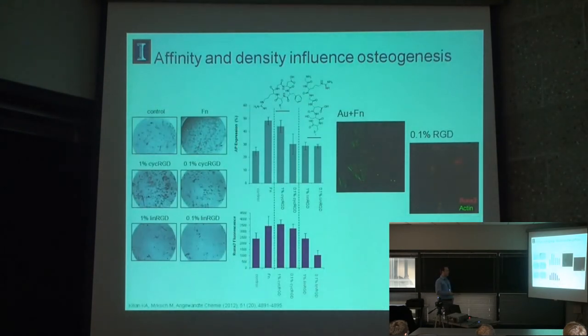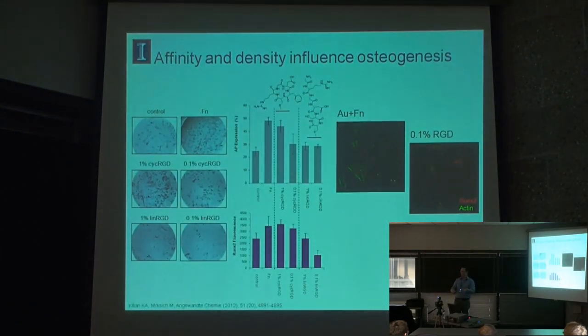And so in our first experiments, thankfully, we decided not to add a bunch of media. We just let them grow, and then we fixed and stained them. And we got some really interesting results. So here we see our control, where with these heterogeneous populations of MSCs, anyone who works with MSCs has seen this. You always get a mixture of cells, where some of them express alkaline phosphatase. And this is likely due to the heterogeneous nature of the culture, but also probably because some of these cells are becoming transit amplifying cells, moving more towards osteoblasts. And so we always get a mixture of these, but when you culture them on fibronectin for 10 days, we see that more of them are expressing alkaline phosphatase.